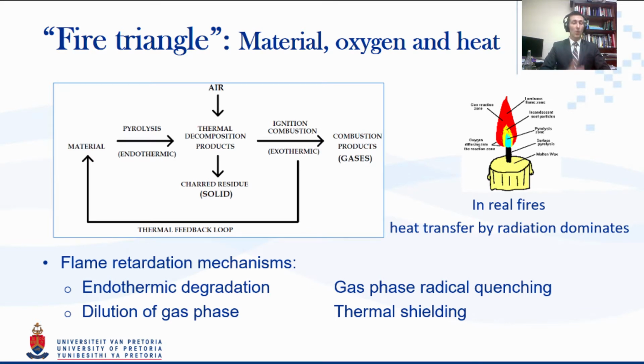So for this reason, there are multiple different flame retardation mechanisms that are used to counteract this sort of rapid fire growth. One of those is endothermic degradation, where energy is taken away from the flame. Another is gas radical quenching, which stops a lot of the oxidation that starts breaking it down. And then there's obviously dilution of the gas phase and thermal shielding. Those last two are of key interest to us because expandable graphite and especially intumescent flame retardants deliver a really good result by making a thermal barrier, and then often to make that thermal barrier, gas is released which expands that outer layer, and that thermal shielding then does both, blocking some of the oxygen transfer but also some of the heat transfer.